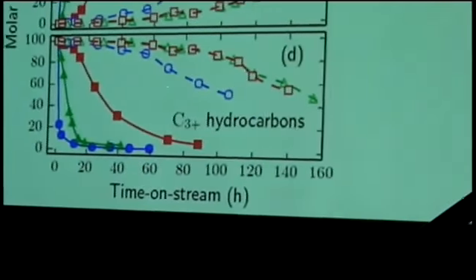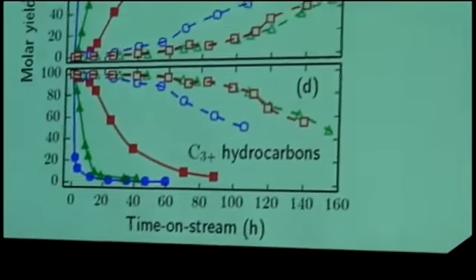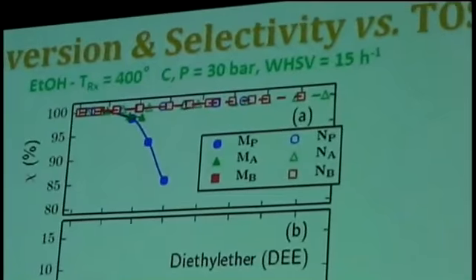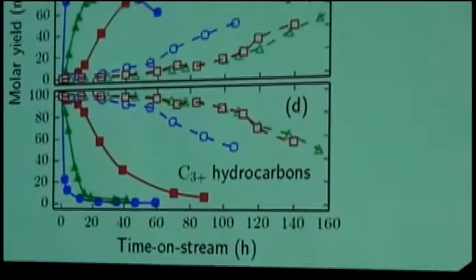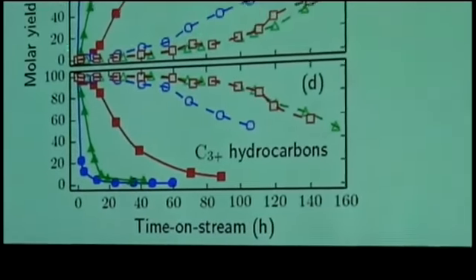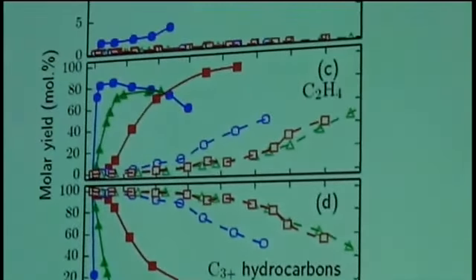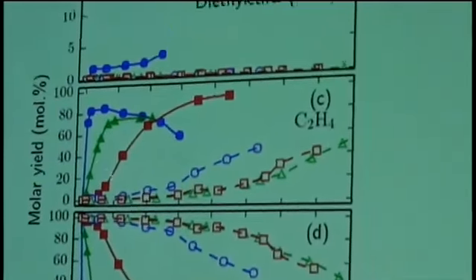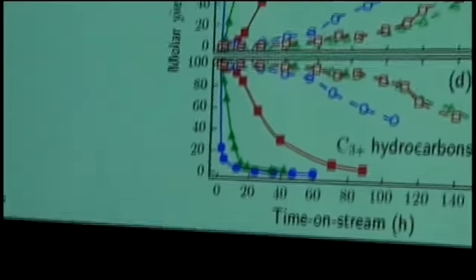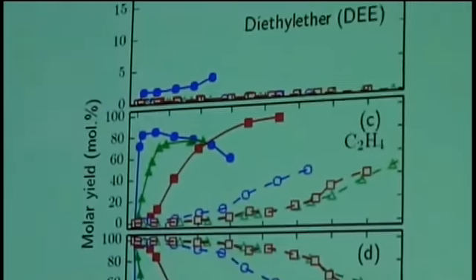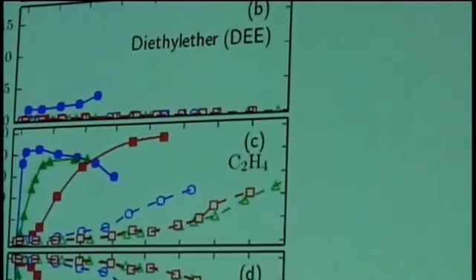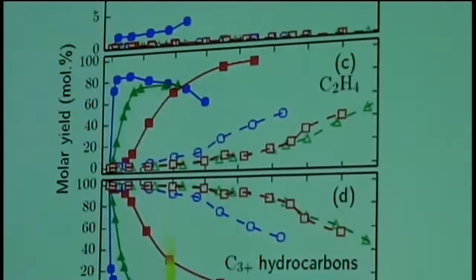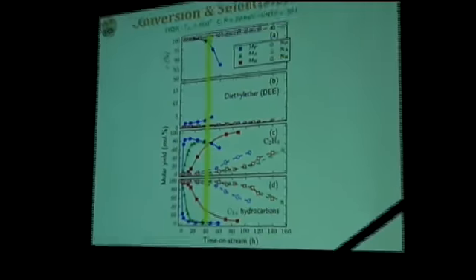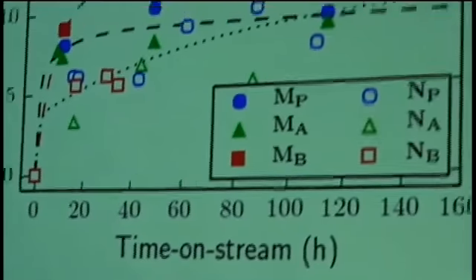But it is no match for the nano-sized zeolite. The starting material is here, and then a little bit of post-synthesis treatment is further improving its performance. Here you see again that the ethylene, which is one of the problems that people want to have, either from ethanol or from methanol, is just appearing very fast but decreases very fast. And again, we see two families: the hierarchical zeolite prepared by post-synthesis treatment, and then the nano-sized zeolite. So we decided to have a look at about 40 hour stream of the catalyst, and now we look at the coke content.